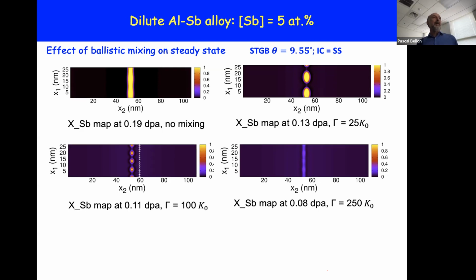So yeah, I see. Now I better understand your question. You're right that in this case there is no coupling between the composition field and the order parameter capturing the dislocations. But Gabriel, in his thesis, studied dislocation climb, and you can add a motion of the dislocation core based, in fact, on the flux of point defects feeding those dislocation cores. So you can physically capture, in a somewhat quantitative way, the origin of dislocation climb or the coupling with composition here. We have not done it yet, but this is on the wish list.